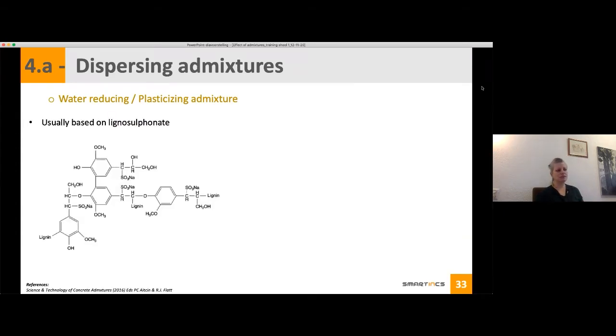About the composition, they are based on lignosulfonates. Here I show a chemical structure. I won't go more into the structure, but what is good to know is that they are a natural product from the wood industry, which means that the quality and purity of this admixture also varies in time. It means the performance of the admixture can vary. For lignosulfonate it is also good to take into account that in the solid content of a spent liquor, you have about 25% sugar. And sugar can cause retardation in your concrete. So you can use lignosulfonate, but depending on your dosage, you should be careful whether it brings retardation to your concrete mix or not.